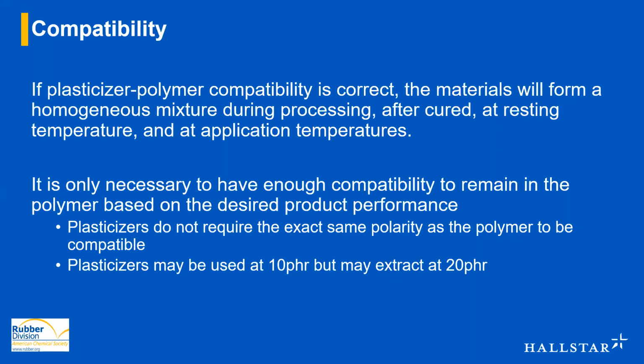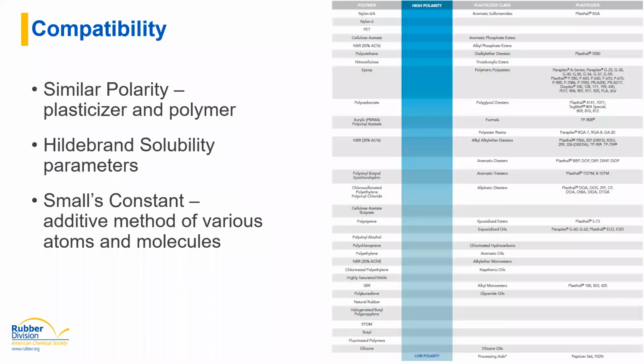And then the numbers given here for loading levels are a little arbitrary, but just to illustrate a little bit, plasticizers could also be used at a lower loading level of, say, 10 parts, but if you increase to 20 parts, you might be pushing past that compatibility threshold and you might start seeing extraction coming out. So loading level is also something to keep in mind when you're looking at compatibility. So as I mentioned on the previous slide, polarity is probably the quickest and easiest way to estimate whether your plasticizer and your polymer will be compatible.